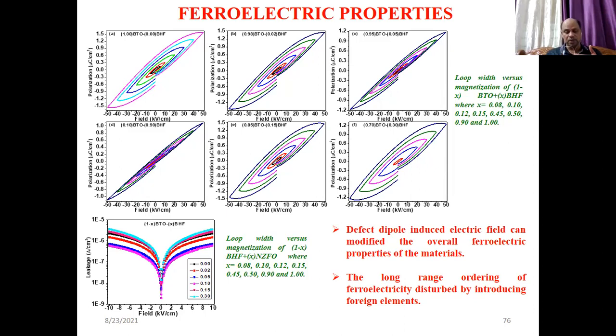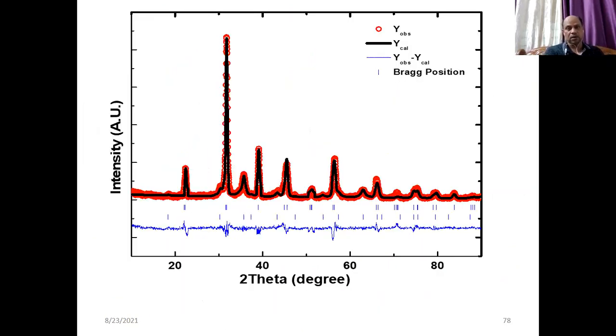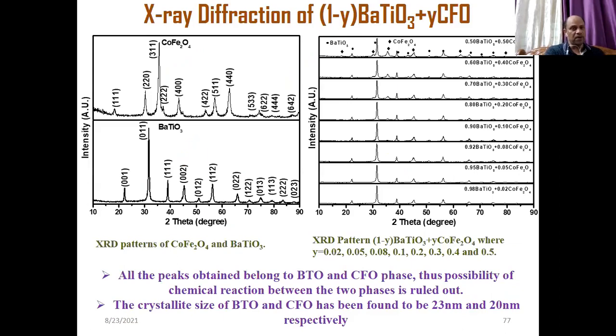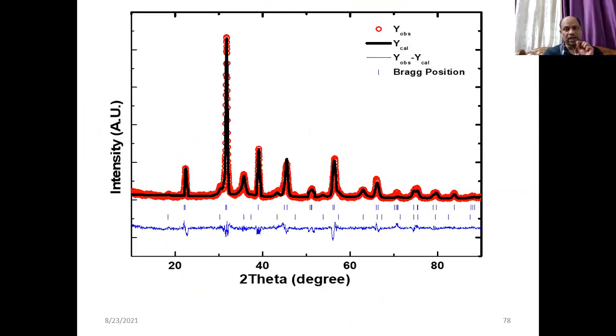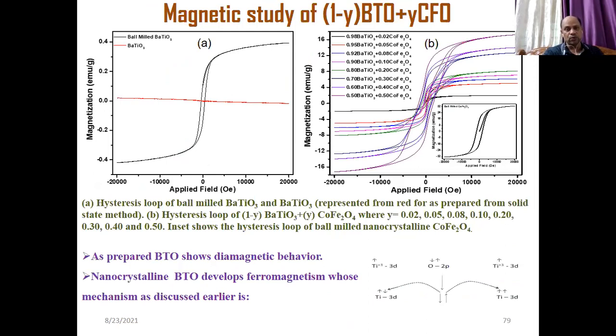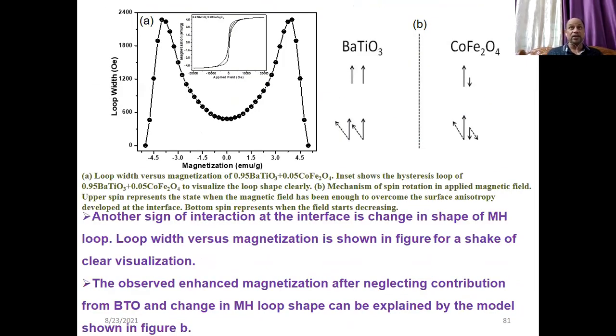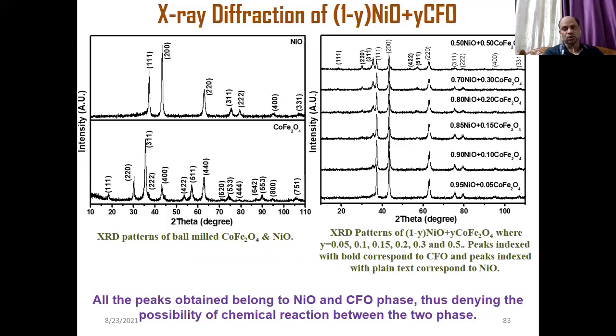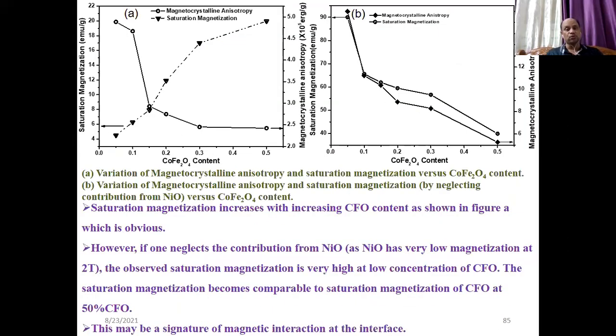And in the case of BHF BTO, we see that their interaction is very little, because BHF is a very highly magnetic material. But in cobalt ferrite and BTO, if you take it the same way and look at their interaction, you will find it is very prominent, because CFO and BTO come a little closer compared to BHF because of their crystal structure compatibility, so it shows better interaction. Similarly, when you go for antiferromagnetic and ferrimagnetic interaction, we found that MS is enhanced due to the interaction.